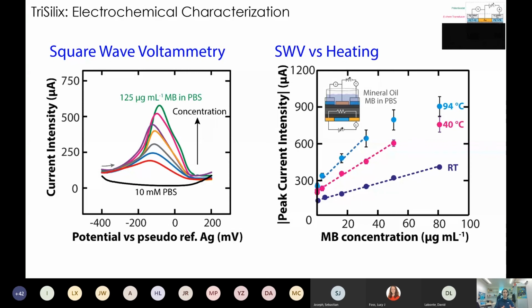And with this configuration, we also have the flexibility to detect low concentrations of the reporter, which is called methylene blue, down to small micrograms per milliliter concentration. So we can really detect very small amounts of the reporter itself, which means that we can detect very small amounts of DNA.